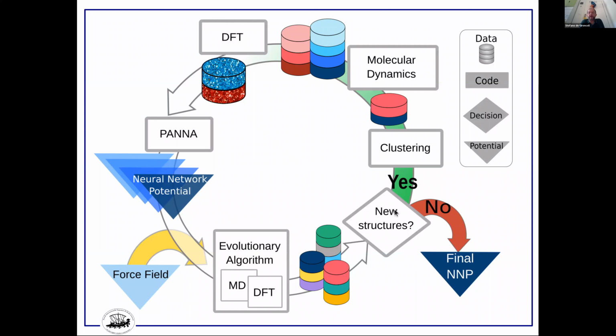If these configurations are many, then you need to do some clustering, similar to the one that we did for glycine, in order to figure out what the representative configurations for your space are. And then once you have found these representatives, you run some molecular dynamics because you want to explore the phase space around the minima. And then from this run of molecular dynamics, you can extract a subset of uncorrelated samples so that you are sampling the thermodynamic phase space, but without too much correlation between one configuration and the next.